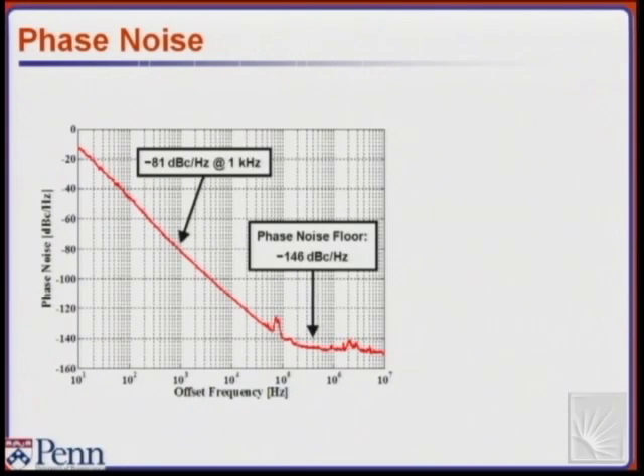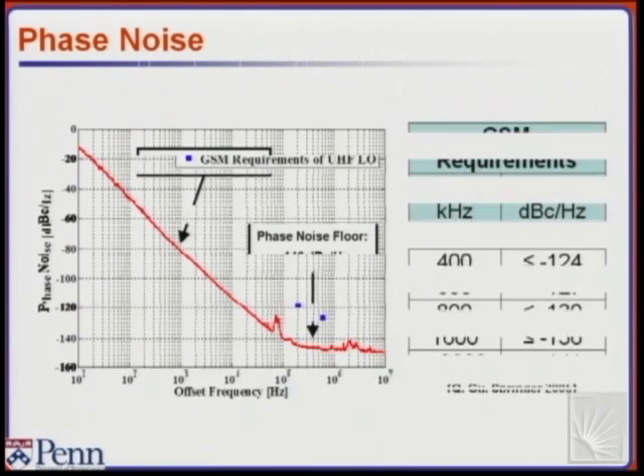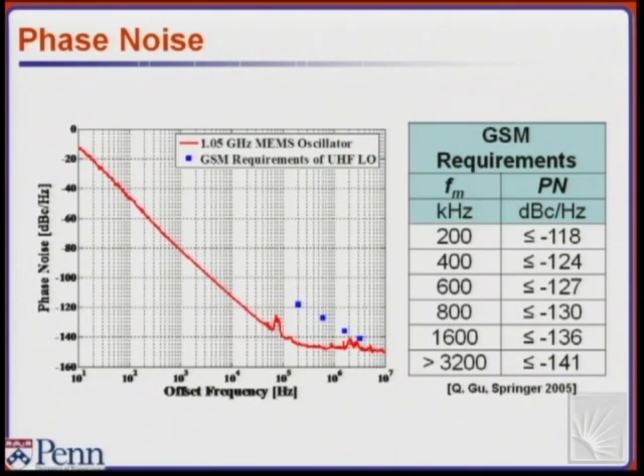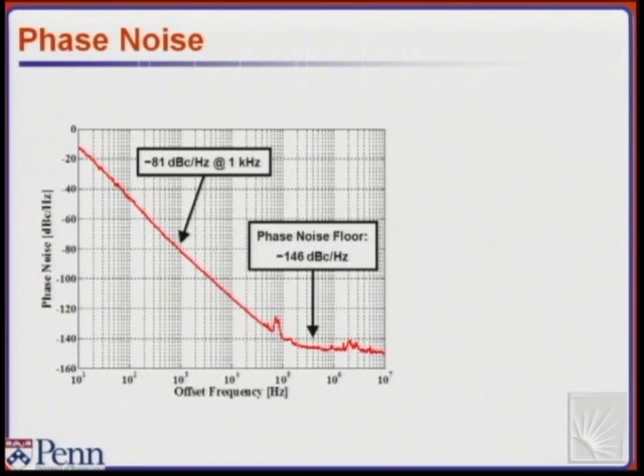We get a floor of about minus 146 dBc per hertz. This is at 1 gigahertz, so it's a 1.05 gigahertz oscillator, sorry. And this is the offset from the center frequency. So above a megahertz, you're hitting the noise floor, and we were getting about minus 146 dBc per hertz. This is mainly limited by the power handling of the device. I told you minus 23 dBm of power output wasn't really optimized. So we could push this even lower, probably to minus 160 dBc per hertz, which would probably make it one of the best oscillators out there at 1 gigahertz.